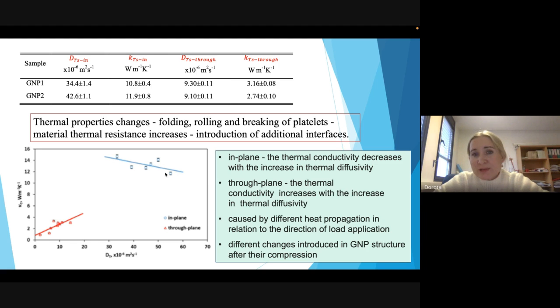When we press the sample, the single platelets are breaking, rolling, unfolding. In such a way, we introduce more internal interfaces in the material, which in turn increases its thermal resistance. So the more pressure we apply to the sample, the more breaking and rolling there is.